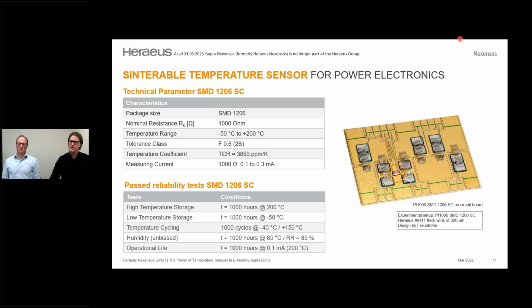We made a lot of tests. These tests are made in coordination with a lead customer from us who is out of the power electronics world to take care that all these tests are the right tests. That means we have a high temperature storage, 1000 hours, 200 degrees passed, everything is fine. Low temperature storage up to -50 degrees, 1000 hours also passed. We cycle our system -40 up to 150. Test passed, everything is fine.